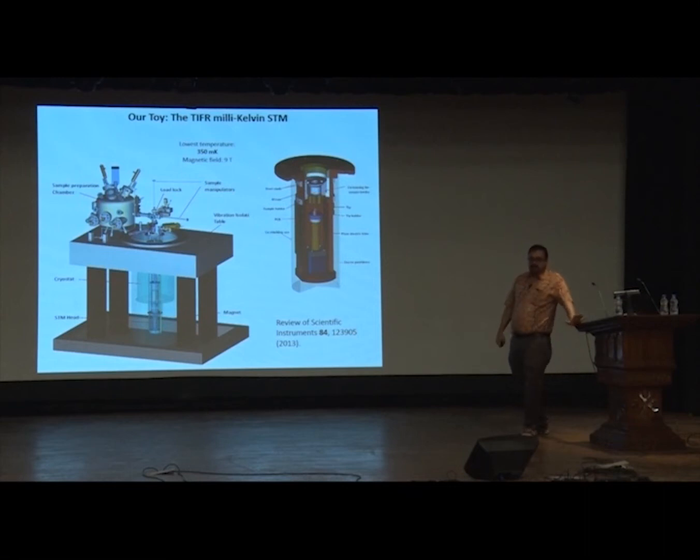Because STM you cannot do on any sample once you expose it to air. All that you get after exposing to air is garbage, because tunneling is from the surface and the surface is contaminated. So we have this chamber in which we prepare our sample if it's a thin film, or we cleave a sample and open a fresh surface if it's a single crystal, and then with the help of these manipulators, without ever breaking vacuum, we push it down to low temperature here. This is our STM head, and if you want more details, you should see this paper where we have published this design.